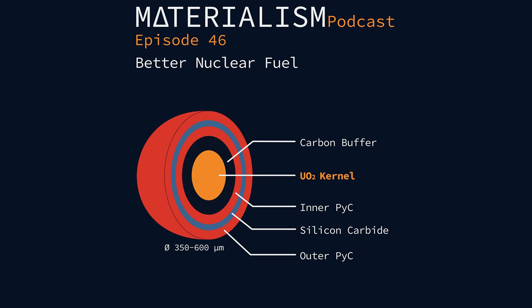So this is typically what they'll do in these test reactors. They'll look for strontium, they'll look for europium, look for cesium, and based on what they find, they know what's going wrong in your fuel. Too cool. So they've done pretty extensive tests. They typically test at different temperatures to see when these things will fail. And they're taking these way above what they would be operating at. They're taking like 1600, 1700 C